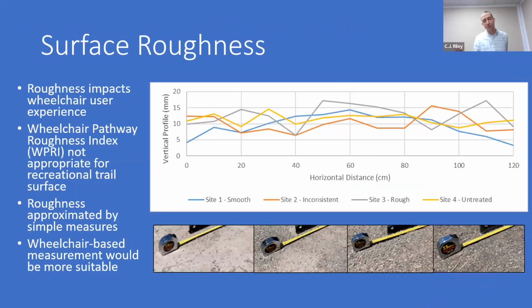We also wanted to look at surface roughness. So somebody mentioned smoothness as a factor, and it certainly is. And in fact, there's a measure called the Wheelchair Pathway Roughness Index and an associated ASTM standard. But that standard really relies on a laser measurement of roughness. And so it's actually inappropriate for something like this with loose material on the surface. It's really intended for pavers or sidewalks or places where there might be gaps that would cause roughness.